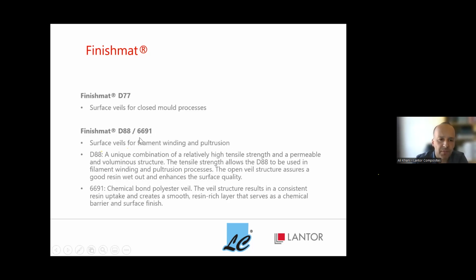So these two surface veils are suitable for filament winding and pultrusion. D88 is a unique combination of having a relatively high tensile strength, but also having a permeable structure. So basically the tensile strength helps to easily use this veil in pultrusion and filament winding. And the open structure helps to absorb resin and enhance the surface quality.